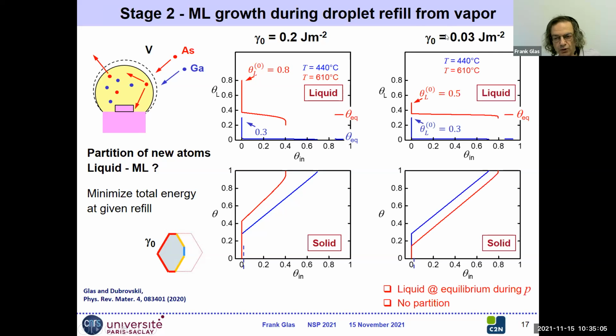If I go now to a lower energy of the monolayer, then whether I'm at low or high temperature, things are fairly ideal. So fast growth of a partial monolayer and then linear increase of the coverage, maybe except at the very end. And in the liquid, then I deplete to equilibrium with the solid, and I stay at equilibrium with the solid during the whole propagation stage, completion of the monolayer. And at higher temperature, it's more or less the case. Maybe you see a small decrease and a small acceleration again, but basically during the whole stage of propagation of the monolayer, you stay at equilibrium.